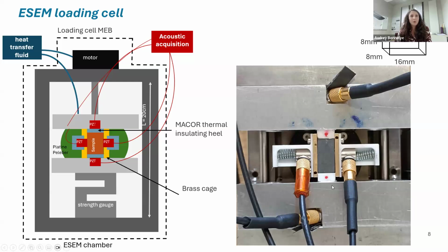So here is how things look. We have a tiny little sample of parallelepipedic shape, of 8 by 8 by 16 millimeters, and we are ion beam polishing the surface. We're using an ion beam polishing device because the samples that we are using are clay, and so we need a very fine polishing if we want to be able to see the very fine microstructure of our sample. So you can see both a scheme and a picture of the assembly. We are measuring the P wave velocity all along the experiment, both axially and radially to our sample.